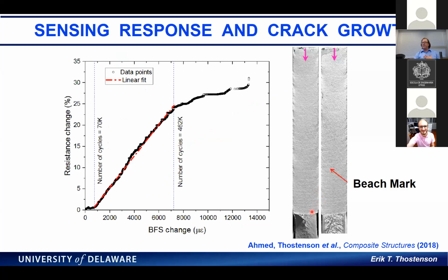My PhD is in material science, so I like to look at fracture surfaces. So we looked and we could see the beach mark. So what we're doing is we're measuring, and using that we can validate the back face strain with our physical measurement of the marks on the surface of the specimen.